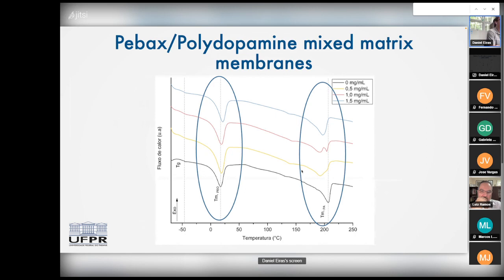So based on DSC results, calorimetric results, we can see that the melting points of the PEO blocks are increasing, while the melting points of the PA groups are reducing. The increase in the melting points of PEO shows that there are stronger interactions between these groups, which means that the flexibility or the mobility of the polymer chain is being reduced. So that explains part of the decrease in the permeability. At the same time, the decrease in the melting point of polyamides, the PA group, indicates that polydopamine might be between the polymer chains, reducing the interactions between them, but at the same time reducing the fraction of free volume.